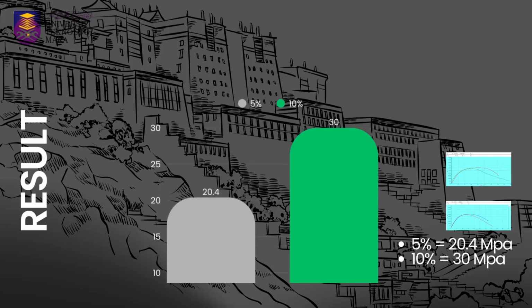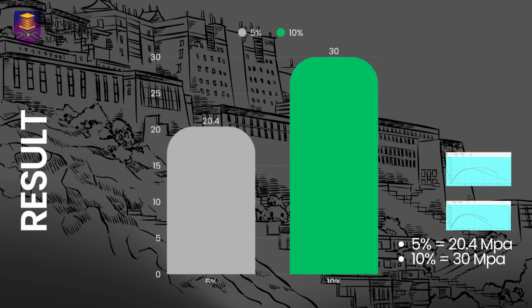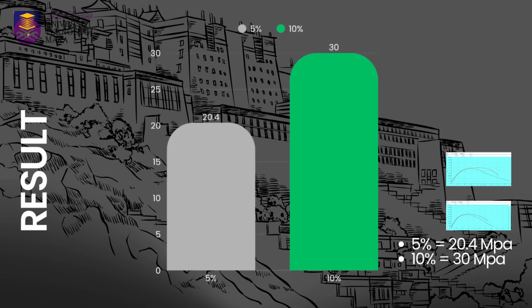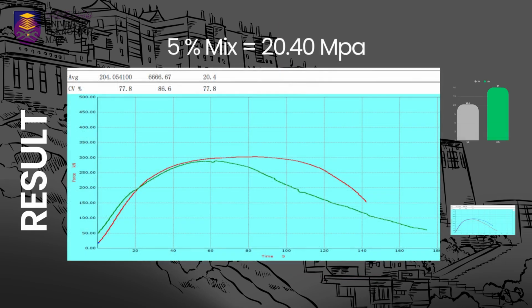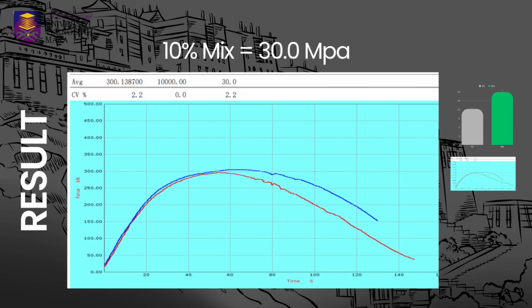The compressive strength test was conducted after 28 days of curing to evaluate the performance of the concrete specimens. The results indicate that the 10% replacement performed better compared to the 5% replacement. This improvement may be influenced by the rough texture and angular shape of crushed ceramic tiles, which can contribute to better interlocking within the concrete matrix. Therefore, recycled ceramic tile aggregates demonstrate strong potential as a sustainable alternative material in concrete production.